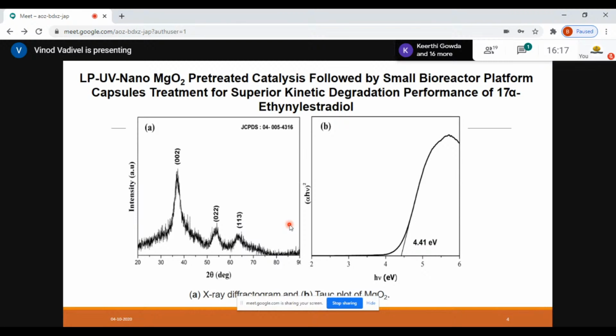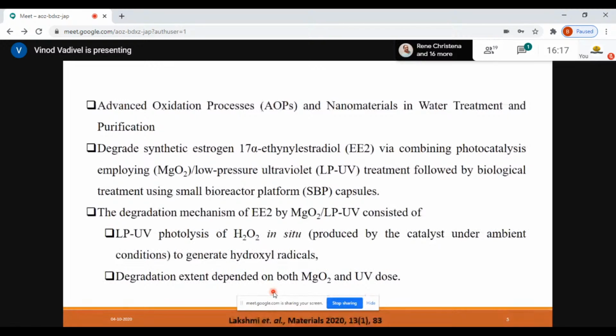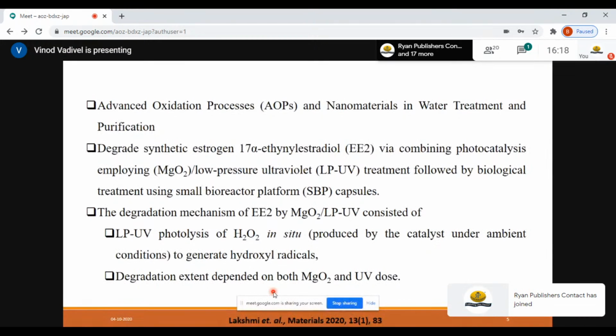So it's a combination of two technologies, photocatalysis followed by biodegradation. The spectra you can see in front of the slides is the XRD spectra, which confirms the phase formation of your MgO2, and the band gap, which is around 4.4. That's the reason we took the UV region, UV spectrum. And the advantage of MgO2, magnesium peroxide, is the in situ generation of hydrogen peroxide.